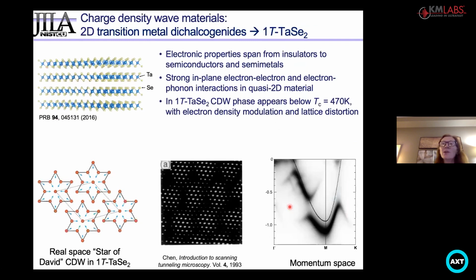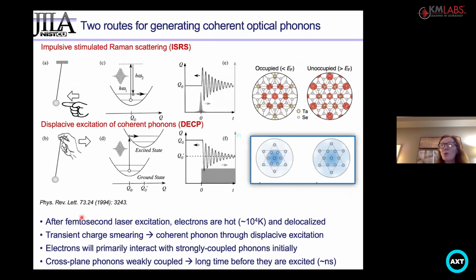So the material we looked at, and we've looked at many materials, we see these phenomena in them, but the one I'm just going to talk about this evening or this morning for you, for those down under, is tantalum diselenide. It's a beautiful material that in its charge density wave phase relaxes into a Star of David order. And so what we do is we heat this material with a femtosecond laser.